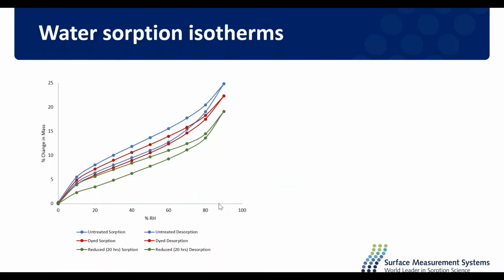And here are some of our results. So I've just got here the untreated hair, dyed hair and reduced hair. And we can see quite clearly that the damaged samples have a reduced water uptake. And this isn't normally what's seen for damaged hair samples. And so that's quite interesting.